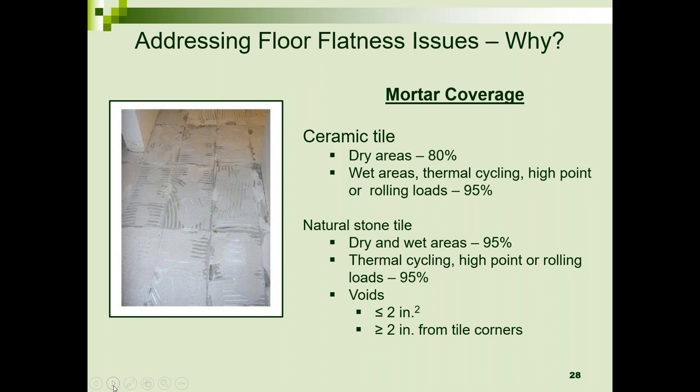So voids under ceramic tile, 80%, under dry areas, 95% if conditions are a bit more aggressive. Natural stone, which is more brittle, again, 95% mortar coverage. So that's very important in a specification to dictate what level of mortar coverage is required, 80 or 95. But that's why it's important to have a level surface or a flattened surface prior to the installation of tile. Next slide.